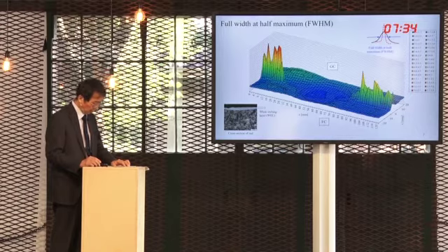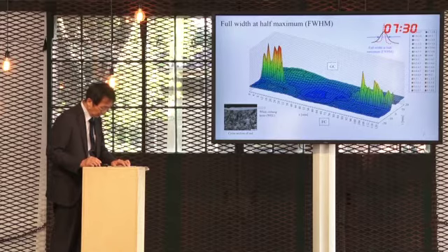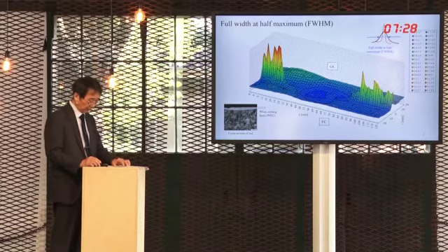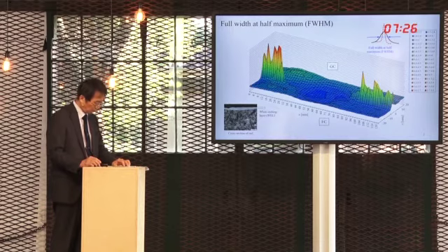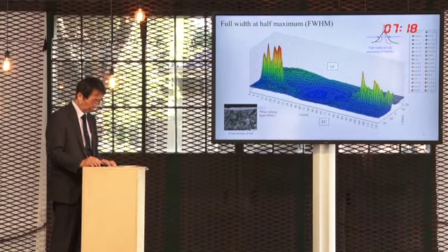Second, we can see a shallow depression around the center of the graph. There was a crack here, so this depression was caused by the crack as well as by the repeated passage of trains after the initiation of the crack.